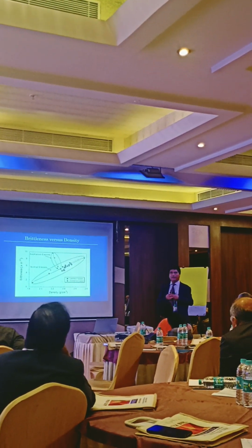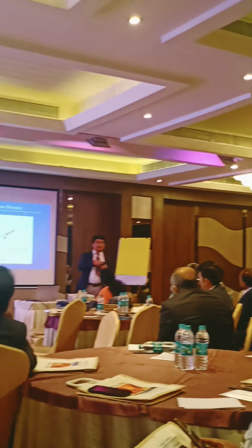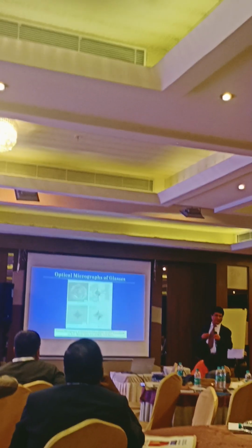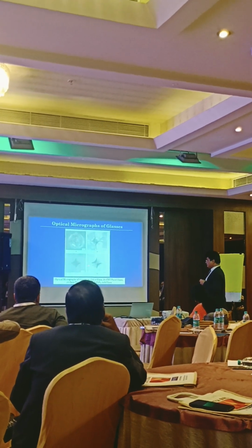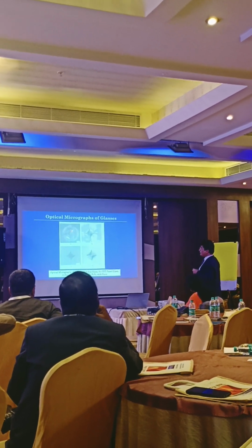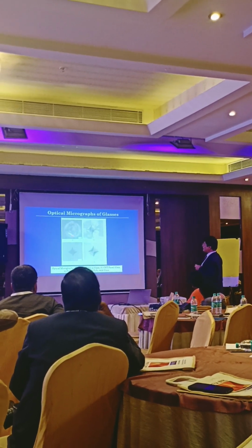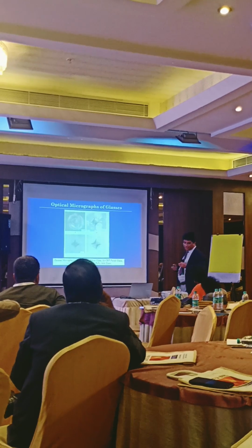Why is that? What we found, I'll explain in the next slide, is that as the density reduces, densification becomes very easy. So when the indentation is penetrating down, glass will densify, it will deform. And the plastic flow is also easy. However, anomalous glasses do not show any plastic flow. These shear lines are indicative of plastic flow. So we can see that there is evidence of plastic flow here, but here this is cracking, not plastic flow. The silica glass just cracks and shows no densification, and doesn't show plastic flow.